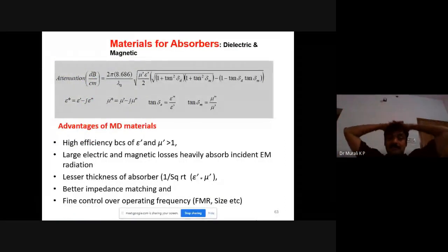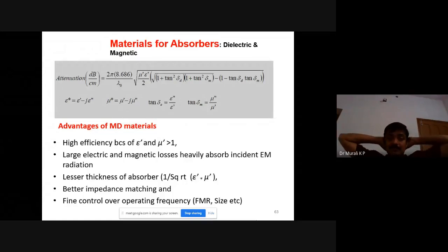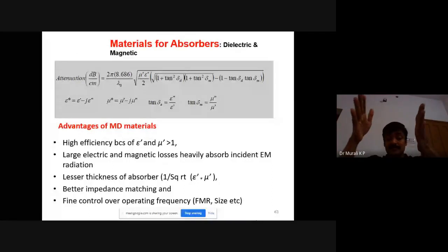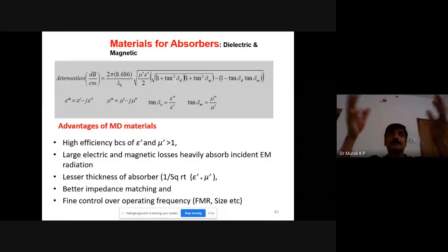In the market you can get both dielectric as well as magnetic materials for these applications. So as you can see, the attenuation formula is given. If you use a magnetodielectric material, it will have very high efficiency because it exhibits both epsilon prime as well as mu prime greater than 1, and very high losses, which heavily absorb electromagnetic radiation. Only lesser thickness is required compared to a dielectric material. Magnetodielectric requires only lesser thickness for the same absorption, and better impedance matching, as I was telling in the previous case, and fine control over the operating frequency, because we can control the resonance frequency to the required frequency range where it is getting fully absorbed.